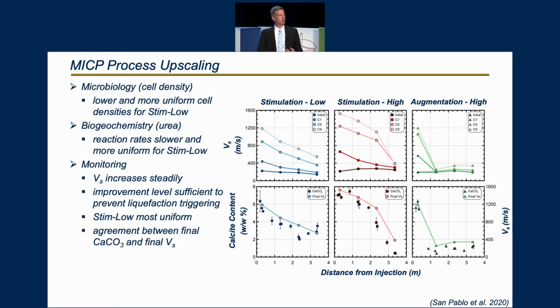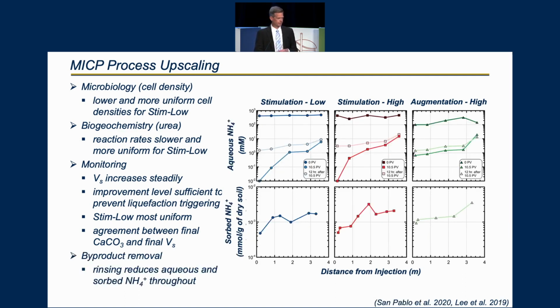The bottom plot now carries down the final shear wave velocity contours, but plots onto it, with a different vertical axis, the final measured calcite content. And I think you can see for all 3 cases the strong agreement between the colored trend lines and the data symbols, indicating the strong correlation between shear wave velocity and calcite content. Again, providing us confidence in Vs being able to help us monitor the progress in real time.